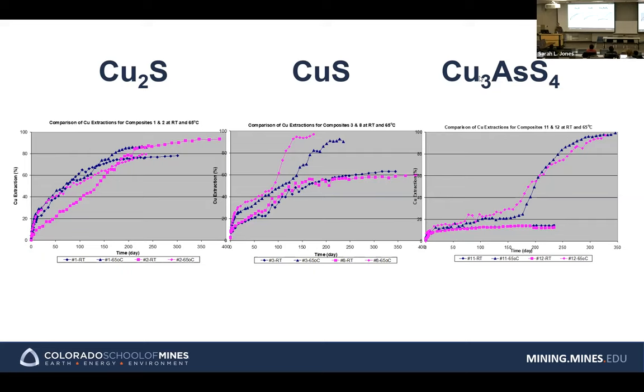And the covellite is here in this material. There's a secondary covellite and also primary covellite. And most of the covellite that we had was a primary covellite. So these are two different things. This one, I mean, all mixed up, but everything is good. But these two, we have two curves here, and two curves there. So the lower extraction represents the lower temperature columns that we used with mesophiles and moderate thermophiles, at room temperature, about 25 degrees Celsius. And the other two are using extreme thermophiles, that sphere-shaped microorganism, at 65 degrees Celsius. So the primary covellite shows better extraction when we use the high temperature microorganism.